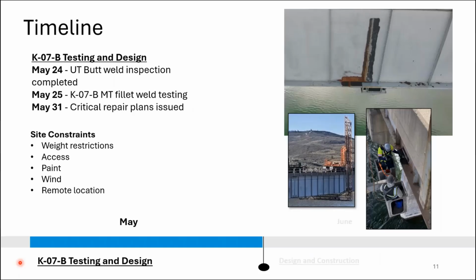Additionally, April in this mountainous region is still part of the winter season. We're still getting quite a bit of wind and weather, and that did restrict the amount of time that our inspectors could be out removing paint or identifying butt weld indications. So it did take us until May 24th to get complete inspection of all the butt welds on Bridge B. Throughout that month, we were actually designing individual repairs for any indications we found and doing additional testing.